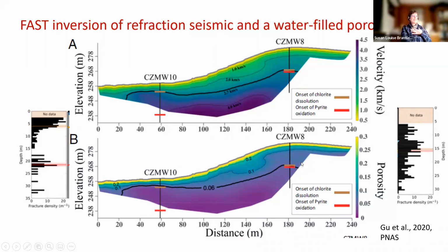And so what I like to think of is that to a great extent, this is where the chlorite weathering begins. And most of this change in porosity is simply from that chlorite dissolution, which creates porosity in the rock. It's not till you get to the shallowest part that illite starts dissolving and the rock actually starts fracturing apart. And that's when you get other increases in porosity.